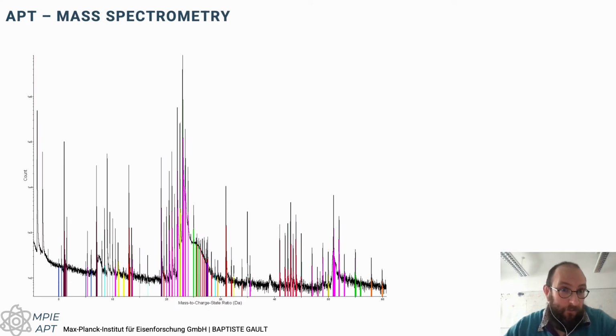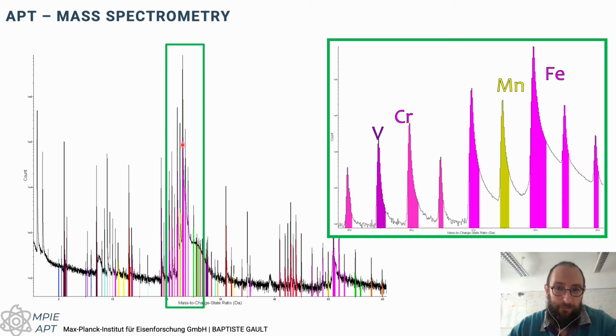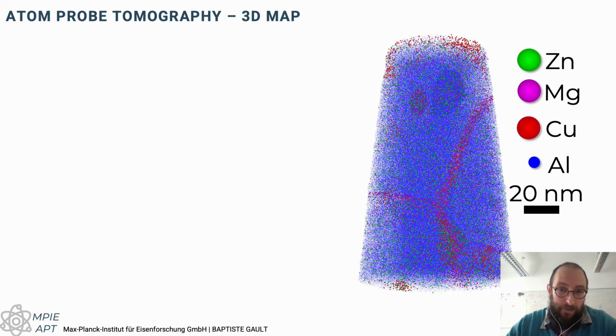So atom probe is primarily a mass spectrometry technique. So we get first a mass spectrum, giving us the quantity of atoms from each isotope that we have inside of the piece of material that we've analyzed. So here, for example, a piece of steel that contains vanadium and chromium. We can see the different isotopes of chromium, manganese, iron. And the relative amplitude of each peak reflects the relative amount of atoms of a specific species within the sample that was analyzed. And the second aspect of atom probe, the strength of atom probe, is its high capability to locate atoms in 3 dimensions.